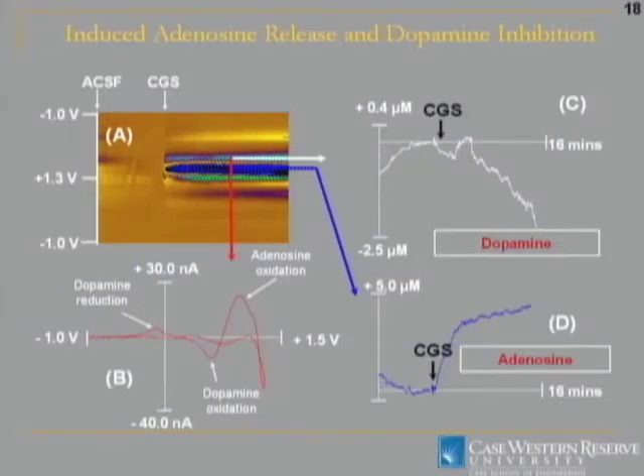Okay, so anyway, we believe that we were able to see adenosine, and we're hoping to continue this and start looking at more relevant questions in terms of the role of adenosine. But what I wanted to point out is that because dopamine does not oxidize at the same potential, we can actually see them both at the same time on the same diamond electrode. And this was some data from a slice, and this is all background subtracted. So it's subtracted from the data taken before you applied the agonist. And consequently, the current went up for oxidation of adenosine, and that's shown down here.